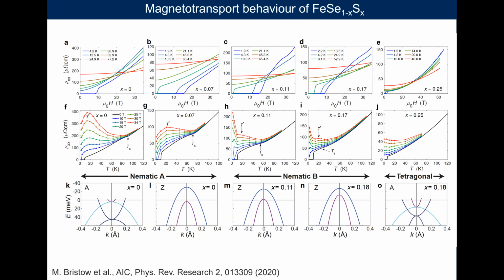But if we also now check the magnetotransport behavior of these compounds, so these are measurements of rho xx, so longitudinal resistivity in magnetic fields to about 33 Tesla. As a function of different concentration, we also notice some peculiar features in different regimes. So for low concentrations, where we only have one hole pocket crossing the Fermi level, what we notice is that the resistivity in high magnetic fields, this is already a factor 2 larger than the upper critical field, still has the signatures as if it has some strong fluctuations, potentially superconducting fluctuations. So it has a peak and then it drops down.